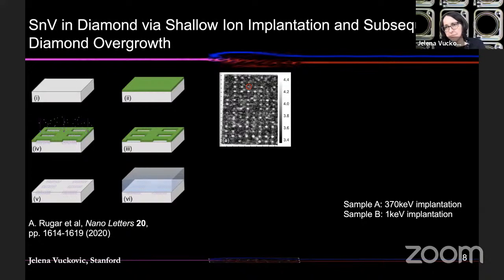And the idea is pretty simple, right? We know that the main problem with incorporation of atoms into diamond is that you have to use a very high energy in order to push this atom or ion inside of the diamond lattice. And in that process, when you use ion implantation or focused ion beam, you damage the diamond lattice and break inversion symmetry. That additional strain affects the properties of the environment and your atom. You can change the transition frequency because of the strain, and you also have sensitivity to electric field. You increase line widths and so on. So that damages everything that is favorable for that particular system.